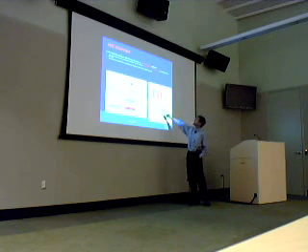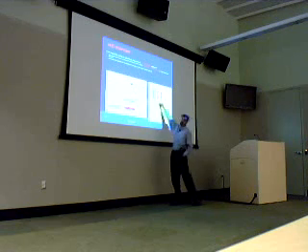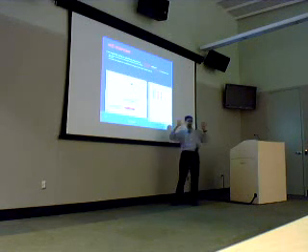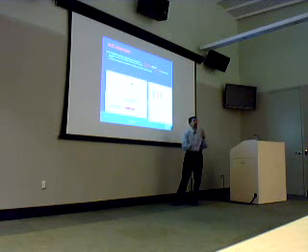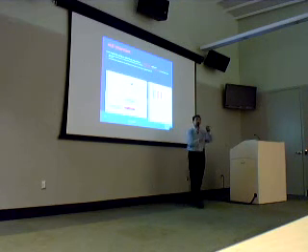So here we are looking at typically a CVD process and an atomic layer process. A CVD process means put all the gases in at the same time. Atomic layer means you put one gas at a time. It has a self-limiting growth. Then you put the other gas and it grows on top of it, so you control the growth. That's what the atomic layer deposition is.